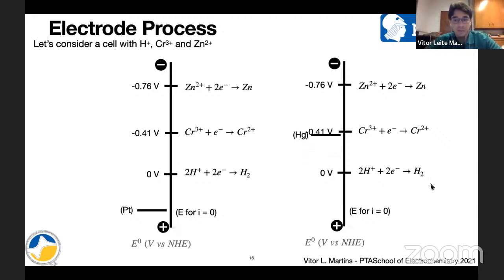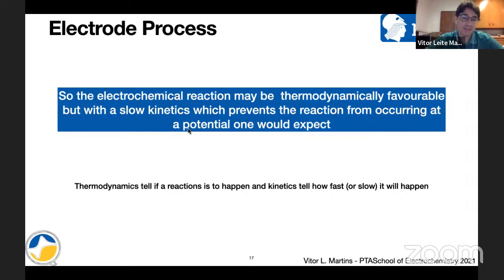And then we keep increasing the potential, and then chromium starts to reduce. You see that chromium is reducing, but hydrogen is not being produced in the mercury electrode. So why is it happening? Why don't we have the reduction of hydrogen in the mercury electrode if we have enough electrode potential for this to happen? So we have enough energy to drive the reaction, but the reaction is not occurring as it happened with the platinum electrode. There's one thing to say.